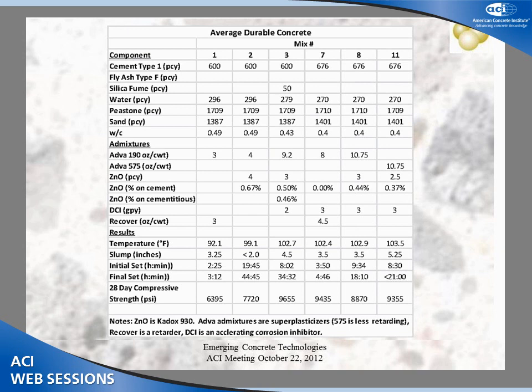The cement content was held fixed, 600 pounds per cubic yard, at a 0.49 and 0.43 water to cement ratio. Okay, the first mix had no zinc oxide in it. The second one had 0.67% by weight of cement, and the third one had 0.46 by weight of total cementitious material, because it did have some silica fume in it, mix number 3.